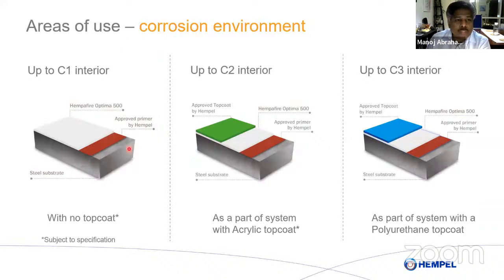All right. So how do we specify? If the corrosion environment is C1, you can apply steel, primer, and then intumescent. You can give a water-based intumescent such as Optima 500. You don't even need a top coat. If it is C2, it is air conditioned, humidity controlled in the Middle East. If you go to Europe, then you talk about heated buildings. So if it is only C2, fairly well-controlled humidity, then steel, primer, water-based intumescent, and a water-based top coat, a simple acrylic top coat that we use for decorating our walls would be good enough.